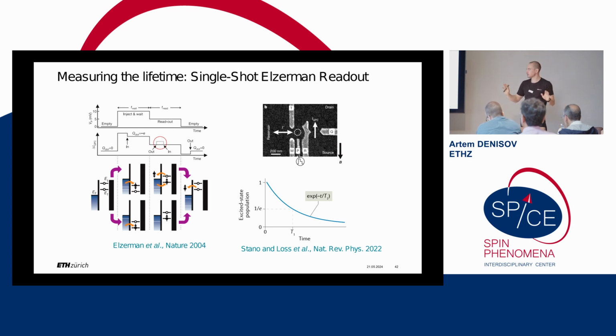So it's just a three-level, very simple pulsing technique, which starts with initialization. When, for example, you have just a spin qubit, you have two states, so you just pulse both your levels above your Fermi level, to load either the excited state or the ground state. And in the second step, you pulse your Fermi level in between your ground state and excited state. And if your electron is still in the excited state, it will tunnel away from the dot. Your dot for some time is going to be empty. And then at some point, your dot should be filled again with an electron from the reservoir, which will tunnel to the ground state. However, if your dot is in the ground state during the second pulse, it will just stay. Nothing will happen. And in the third pulse, you just pull all the states very far to reset your dot and just continue this again and again to collect statistics.